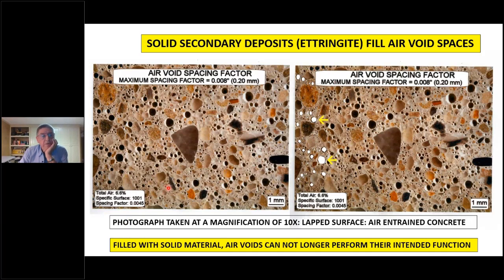These two pictures are microscopic shots of lapped surfaces of a good quality air entrained concrete at 6.6% air. As you recognize, all the little black dots there are air voids. What I'm saying is that if you consider that this is the joint area here, during cycles of freezing and thawing, during cycles of moisture migration, secondary deposits are moved to the air voids and they do get filled. And I'll show this in the petrographic evidence.